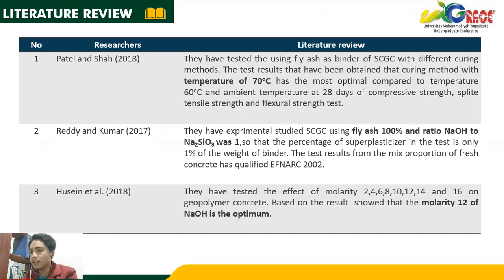And second, Reddy and Kumar 2017, they experimentally studied SCGC using 100% fly ash and a ratio of natrium hydroxide to natrium silicate of 1, with the percentage of superplasticizer in the test only 1% of the weight of binder. The test result from the mixed proportion of the fresh concrete qualified EFNARC 2002. And last, Husein et al. 2018, they tested the effect of molarity from 2 to 16 on geopolymer concrete. Based on the results, the molarity of 12 of the natrium hydroxide is the optimum.